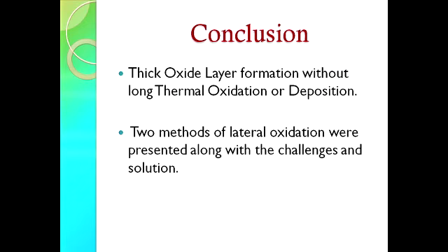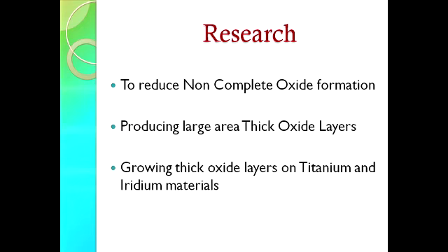So we saw about two methods of lateral oxidizing process that can replace long thermal oxidation and deposition techniques to form thick oxide layer. So there is research going on to reduce the number of voids formed in the process, and also to form large areas of oxide layers. And even this method is extended to titanium and other materials to form thick oxide layer for insulation. Thank you.